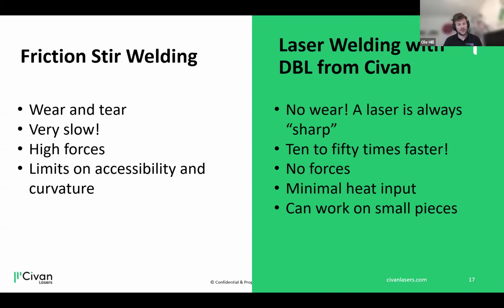And this has, to be fair, an advantage of not exploding any residue gas that is inside because it is relatively cold at something like 300 degrees or 400 degrees. But it is very slow and you need to apply a lot of force on the workpiece. Also the pin itself is subject to wear and tear, so you need to keep replacing the pin every roughly 1,000 meters of welding, and you also have a deteriorating welding quality over this period as well. If your tool is getting less sharp, of course you need to watch out for defects.